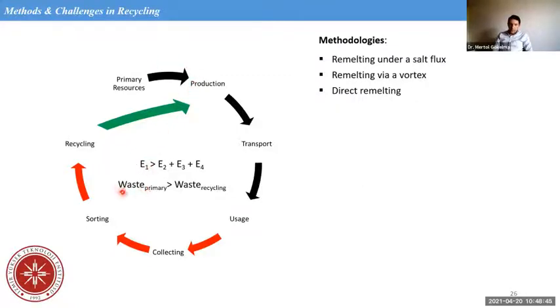In addition, the waste we produce in primary is always bigger than the waste we produce in recycling. In recycling, the methodology is usually remelting under a salt flux because of a lot of oxides, and it can be remelting via a vortex, especially for small size scraps so that they don't float and oxidize. And the third is for easier, cleaner scraps, direct remelting.